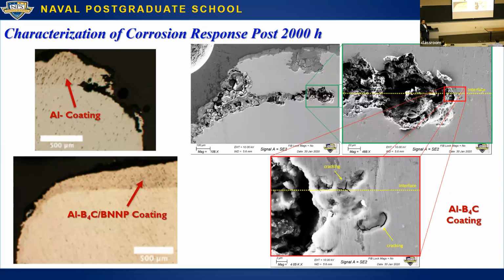You don't see that in the composite. In the composite, we think that the BNNP and B4C to some extent are able to at least reduce some of this current, which is one of the driving mechanisms for corrosion. We're slowing down the current. And we think that's why we didn't get that in the composite. And then this is just essentially the interface of the B4C coating. The B4C alone was not giving us the same effect. So we do think that it was the platelet morphology that was letting us form, even at very low compositions, a good percolating network of that.